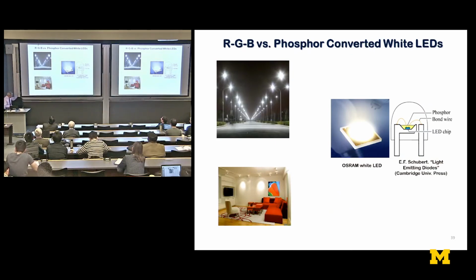One other interesting application of these, now that we could make red quantum dots and all the other colors, green and blue and so on. Now, coming back to solid-state lighting, what we have now and what we call solid-state lighting is really not solid-state lighting. What we do is we excite yellow and red phosphors with a blue LED. And in such phosphor-converted LEDs, you have internal losses due to Stokes shift. You have backscattering of the pump and converted light by the phosphor layer, and you have non-radiative internal losses. In addition, you have poor temperature stability and reliability, and actually all the money goes in developing and improving that phosphor. The blue LED is perfect. It has quantum efficiencies approaching 90%. I would say almost 100%. But what is really needed is an all-semiconductor converter LED or an RGB.